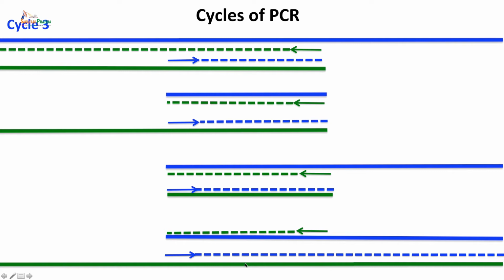So every cycle, you notice, from 2 to 4 to 8, the amount of DNA is doubling with each cycle. And now that in the third cycle you see that the original template, which was very long, and therefore the complementary strand was also very long, this becomes a minor component of the entire reaction, and these shorter products become a major component of the reaction. So with each subsequent cycle, these shorter products will predominate the reaction, and ultimately they will overtake, and they will be so much in abundance that when you analyze you will not even see these longer products, depending on the sensitivity of your measurement of how you visualize the product. These shorter products are the only ones which will be visualized in your agarose gel.